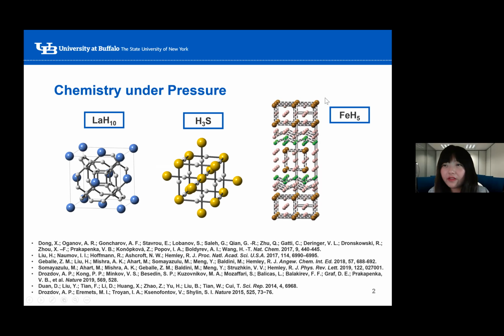However, not all of the high-pressure hydrides would have high TCs. For example, FeH5 showing here was also synthesized under pressure with bulk atomic hydrogen, but no superconductivity was found.